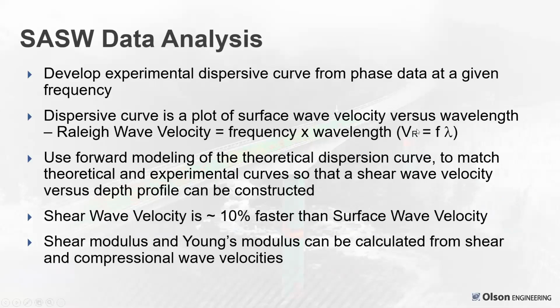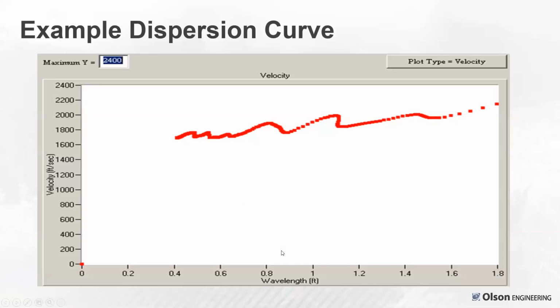Again, depending on velocity equals frequency times wavelength for the Rayleigh wave or surface wave, and use forward modeling. On this project we don't always need to do that, but we did it on this project to match the theoretical and experimental curves. So you can get a shear wave velocity versus depth profile. And the shear wave velocity is approximately 10% faster than surface wave velocity in concrete and masonry. And from that, you can calculate, with assumptions of density and Poisson's ratio, shear modulus and Young's modulus.